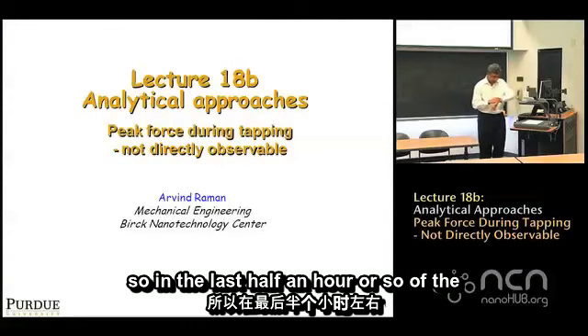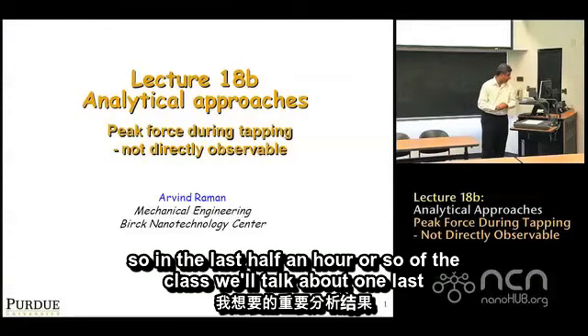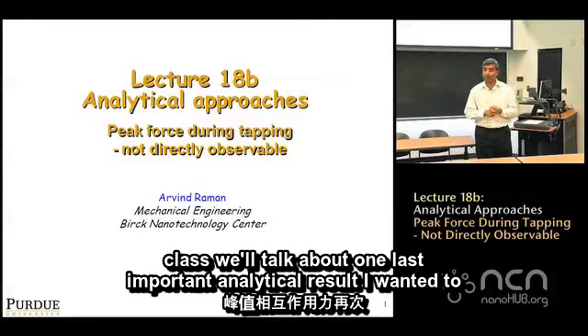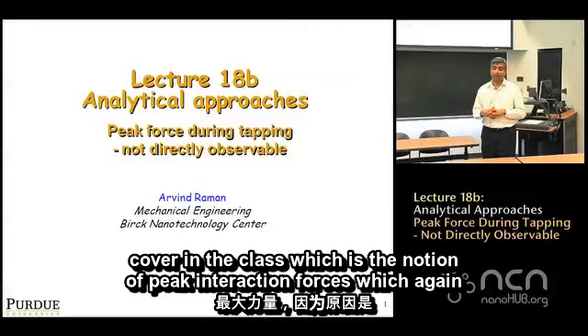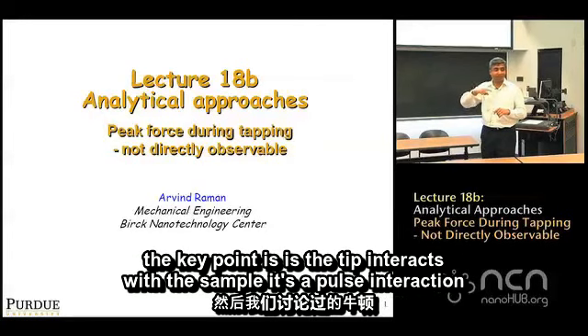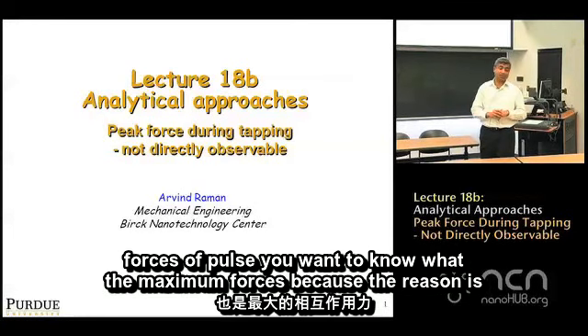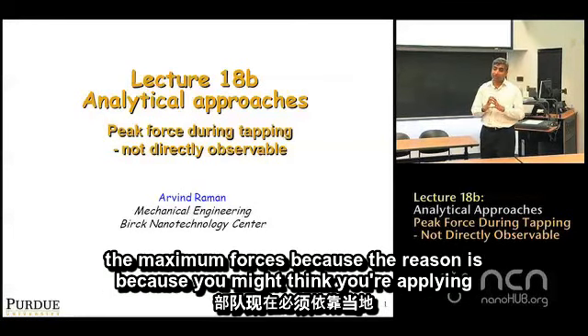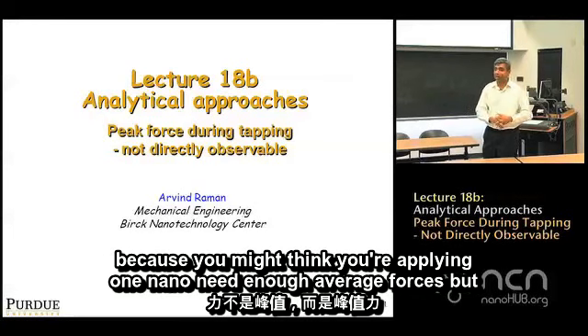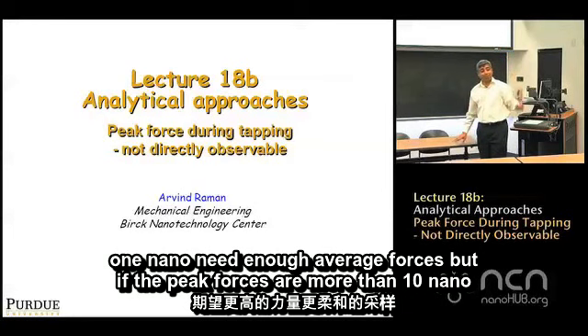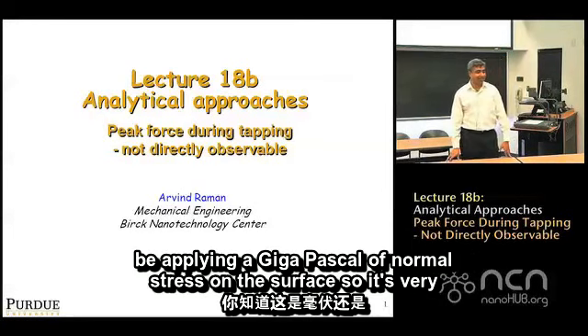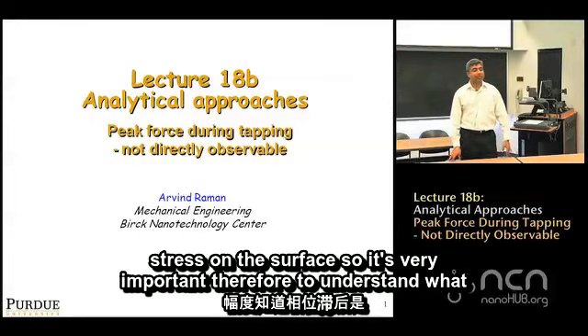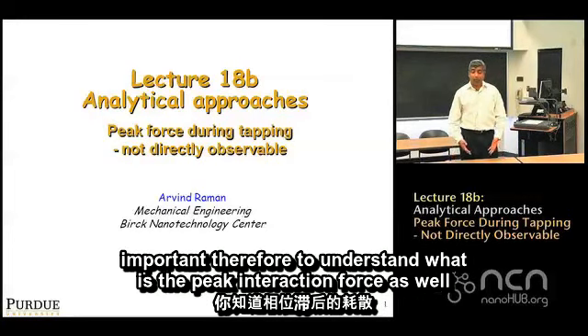In the last half an hour of the class, we'll talk about one last important analytical result: the notion of peak interaction forces. The key point is the tip interacts with the sample as a pulse, and you want to know what the maximum force is. You might think you're applying one nanonewton of average force, but if the peak forces are more than 10 nanonewtons, you might be applying a gigapascal of normal stress on the surface.